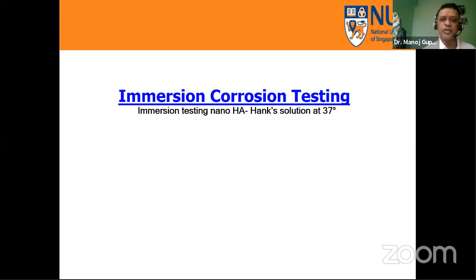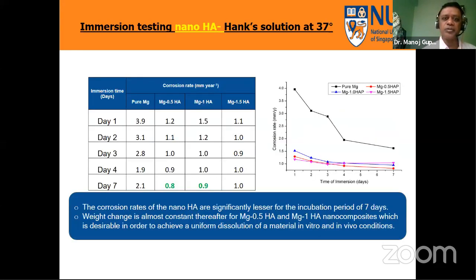We also did immersion corrosion testing in Hank's solution. For the composites with nano hydroxyapatite, the corrosion rate is about 0.8, 0.9, and for Mg 1.5 HA it is 1. These numbers are not too different, but they increase with an increase in the amount of reinforcement. The other way to look at it is that the corrosion rate due to the presence of HA is much lower than pure magnesium, so it is a beneficial effect of the nano reinforcement to improve the corrosion response of this material.